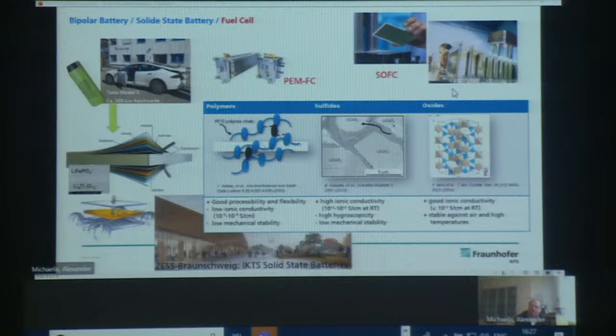As I said, there are still technological challenges to really realize this on a technological level, but we are confident that we are able to do this because we already did it for another technology. So this solid state approach, this stack approach, is already realized in fuel cell technology. When you look into a PEM fuel cell, so polymer electrolyte membrane fuel cell, such an approach is realized. You have a stack technology, you have a polymer for the ion conductor, and these systems already work well. And also for the oxide systems, we have these solid oxide fuel cells where this is also already shown.